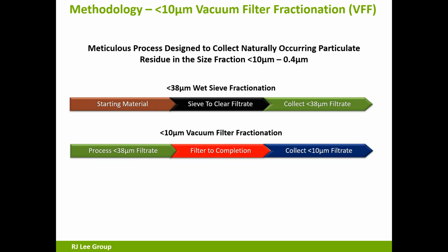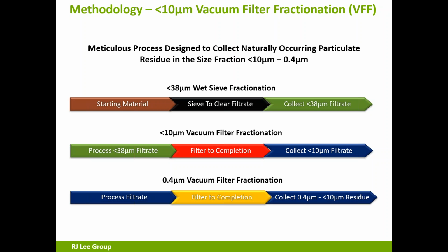That's the starting material before the 38. So by the time we're done, we're down in the micrograms or milligrams. A very small amount of material, so we get nice even layering on the filters, so we don't get compaction. And we collect the 10 micron filtrate. This is the stuff that counts.